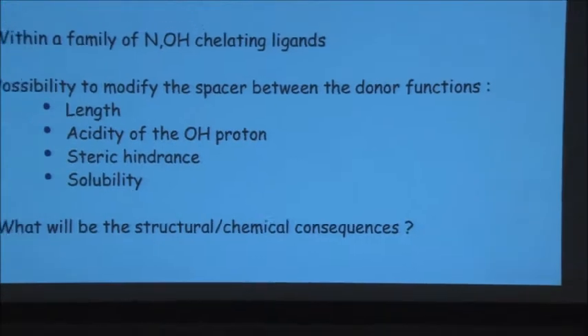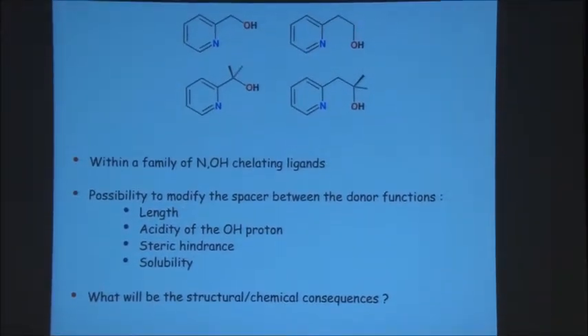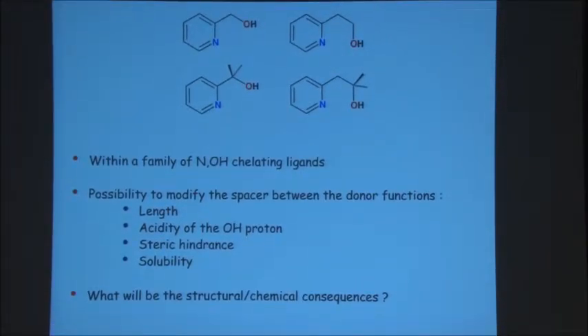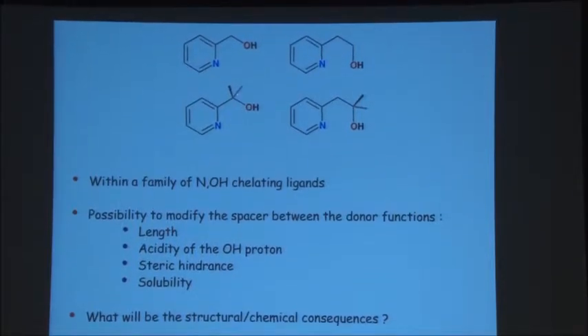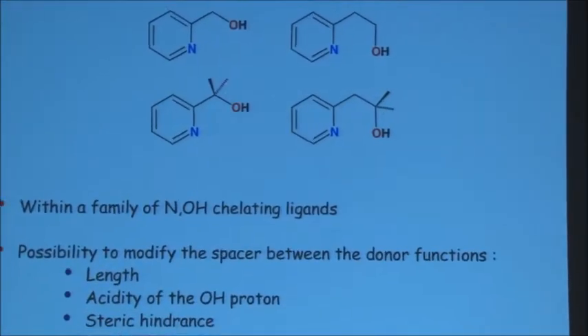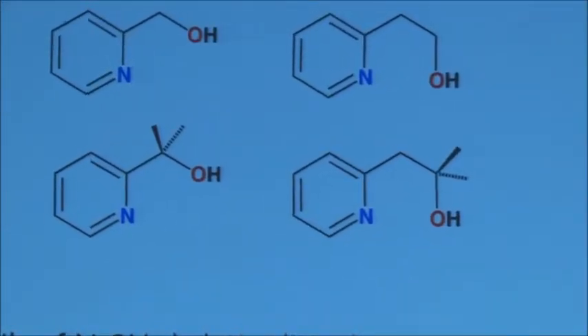Now we think about varying the structural unit, because we know that the ligand is going to have an impact on the catalysis. So is there a way to improve the activity or improve the selectivity? For that, we focused on these very simple systems: pyridine alcohol with just 1 carbon as a spacer between the heterocycle and the alcohol, the C1 spacer, or a C2 spacer. Or here you can put 2 methyl groups in the gem position.